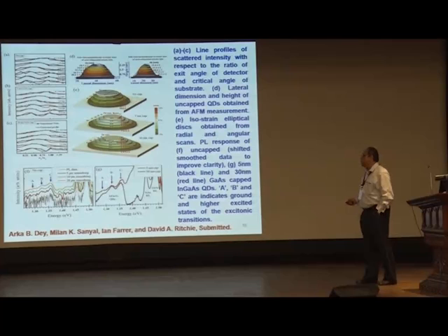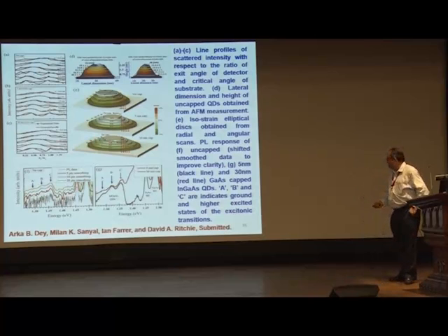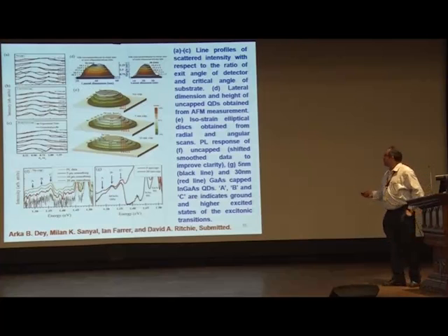And then, as I told you in my earlier transparency, by looking at the position of these peaks, you can find out the size, and of course, you can cross-check with the X-ray and put this together, and then also the composition which is coming out from here can be extracted from PL, assuming that the excitonic volume, the amount of quantum dot that is excited, the exciton is stationed around the base of the quantum dot. Keeping all this in mind, you can really correlate them pretty well, and this is what we have just submitted for publication.